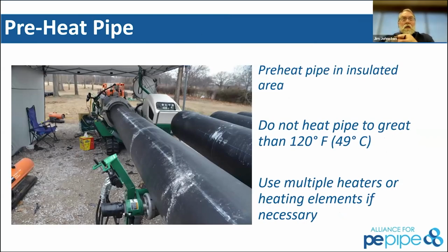So one of the options as we get into this is to preheat that pipe. As Rick talked about for the electrofusion, where you want to have stability of pipe, you want to make sure that you're going to be bringing this pipe up against a heater that's 450 degrees, but you don't want a huge shock to that heater, because you're still trying to melt the ends of that pipe. So it helps to preheat that pipe. Try to do that in an insulated area. We see a lot of pipe being maintained in a tent by itself. You don't want to heat it to greater than 120 degrees, just because you're starting to get into zones where you don't want to mess with the sag of the pipe or any other components. And use multiple heaters where you can.